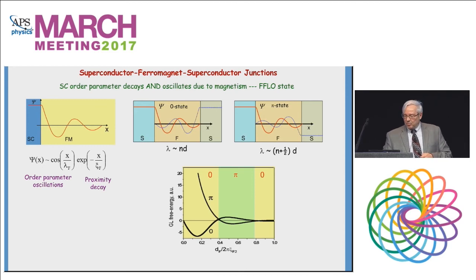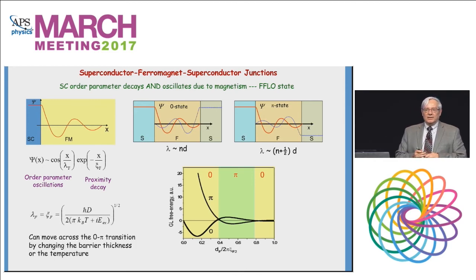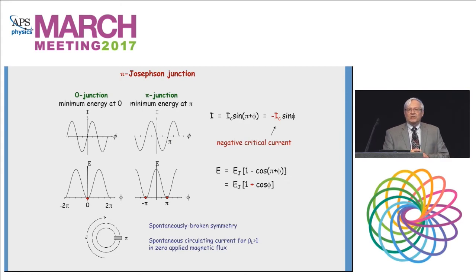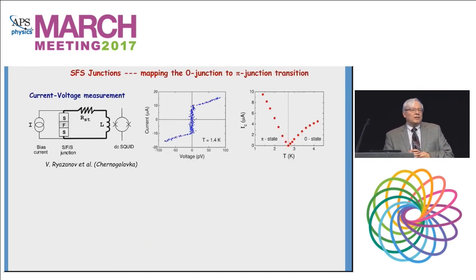That's been measured by many groups. Another way to do it is to look at the temperature dependence, because it turns out these coherence lengths are actually dependent on the temperature, so you can take one junction close to the 0-pi transition and track out this transition directly. So a pi Josephson junction, just to make it clear, is actually a Josephson junction with a negative critical current. And the important thing about it is it has, as I said, a minimum energy at pi as opposed to a minimum energy of 0. So if you look at the current voltage characteristic of such a junction, what you can observe is as you change the temperature, the critical current comes down, goes to 0, and comes back up.